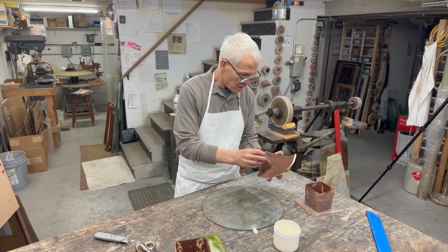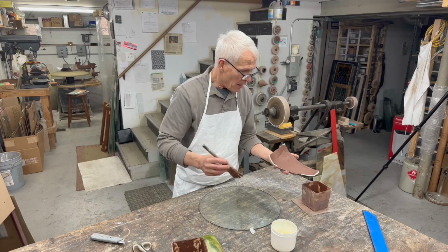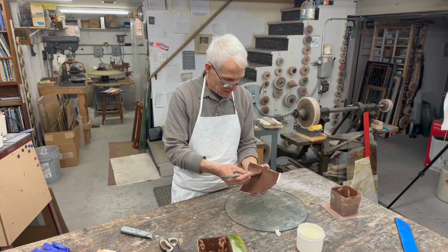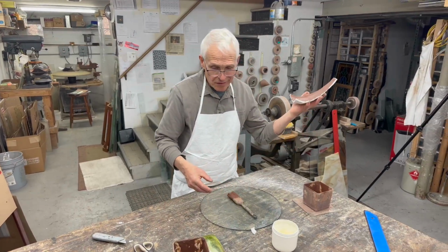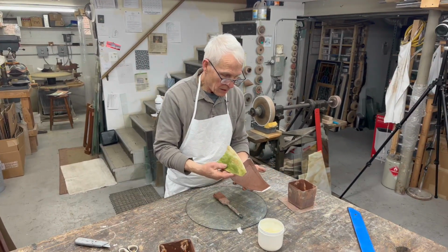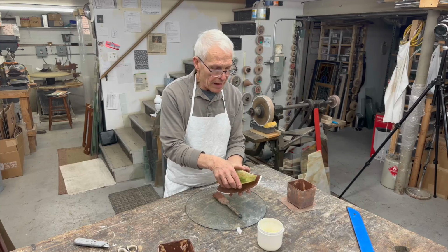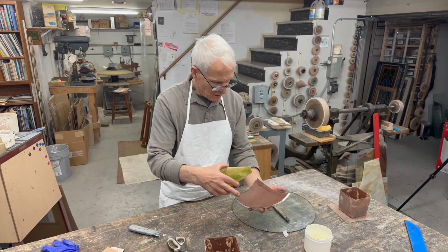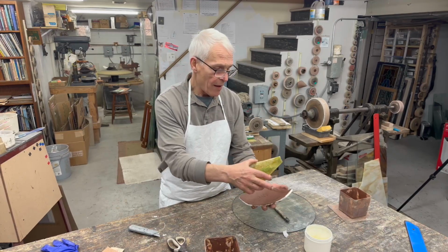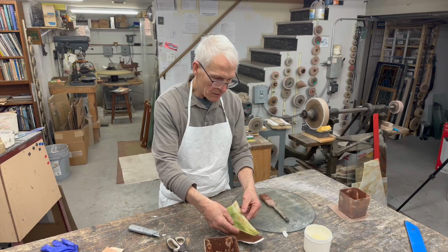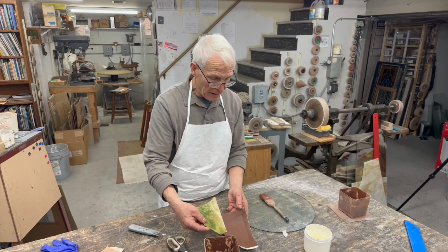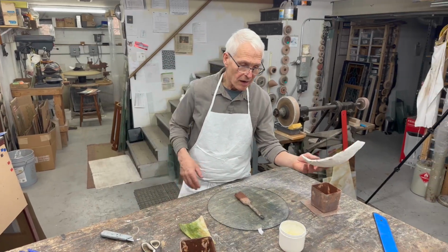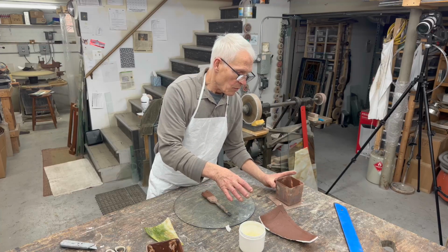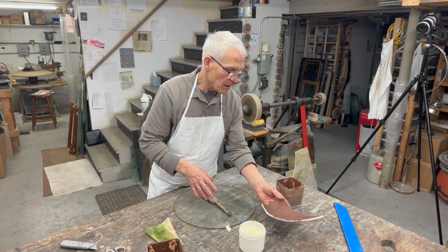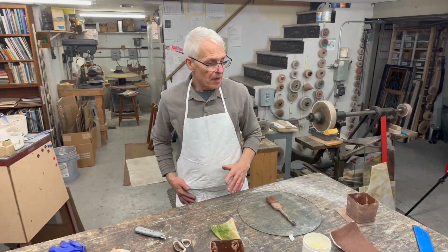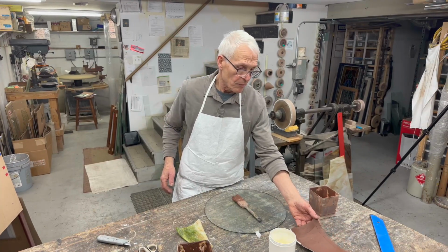And then once again, this needs to dry, and at that point, once it's dry, we'll clean our blank off and get the Vaseline off of it, put it on there, and maybe take a graphite pencil and put our boundary lines so that when we put our flat blank on there and slump it, we'll know about where we want it to land. So this has got to dry. This won't take anywhere near as long to dry as it did with the wet blank. This will probably take an hour or two. You could accelerate that in the kiln.